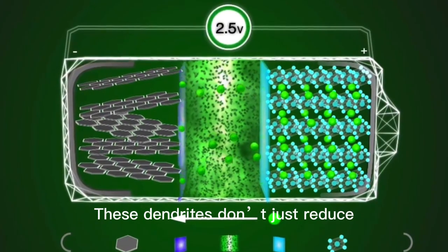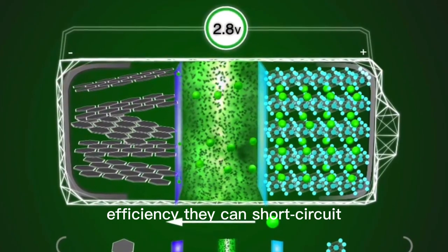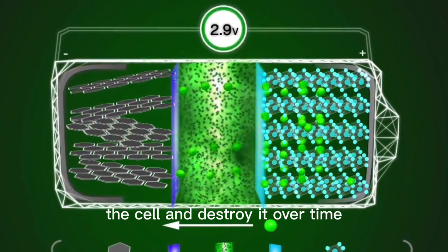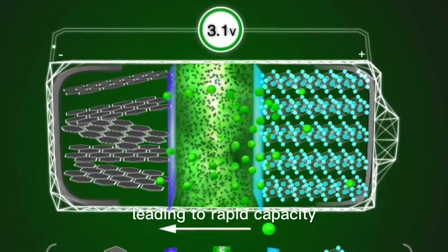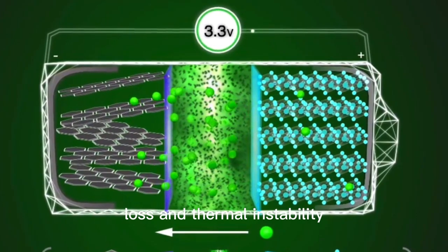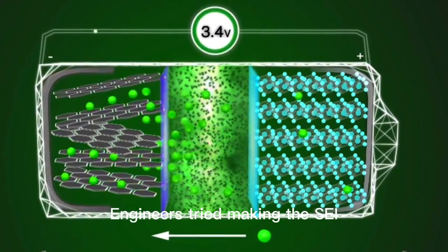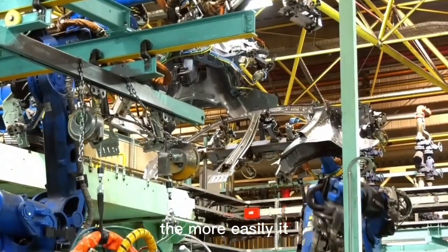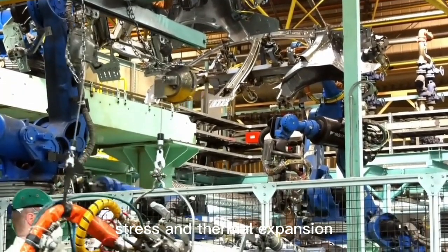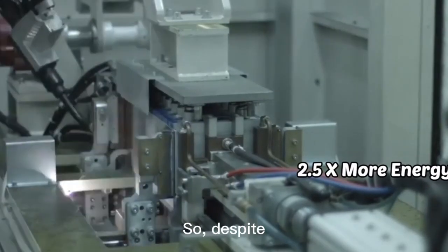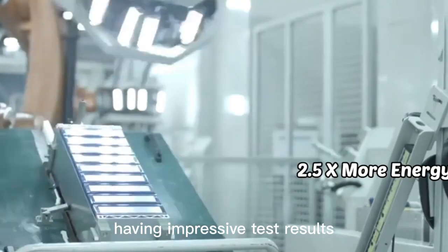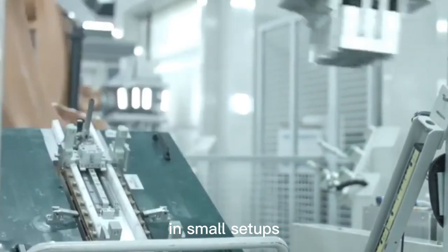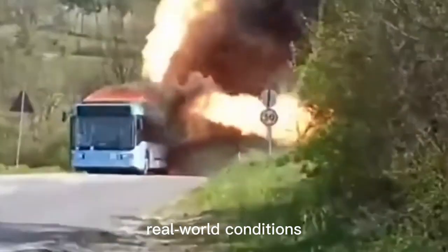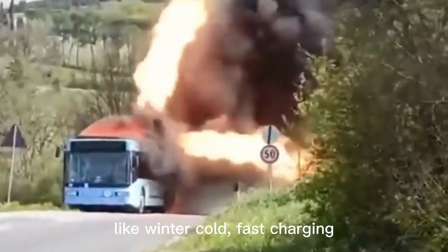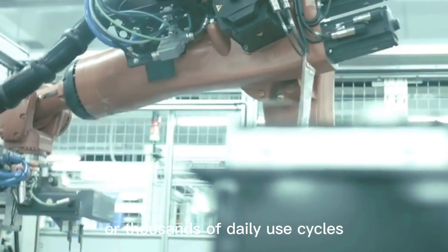These dendrites don't just reduce efficiency. They can short-circuit the cell and destroy it over time, leading to rapid capacity loss and thermal instability. Engineers tried making the SEI harder to resist damage, but the harder they made it, the more easily it fractured under mechanical stress and thermal expansion. So, despite solid-state batteries having impressive test results in small setups, they failed when scaled up for real-world conditions like winter cold, fast charging, or thousands of daily use cycles.